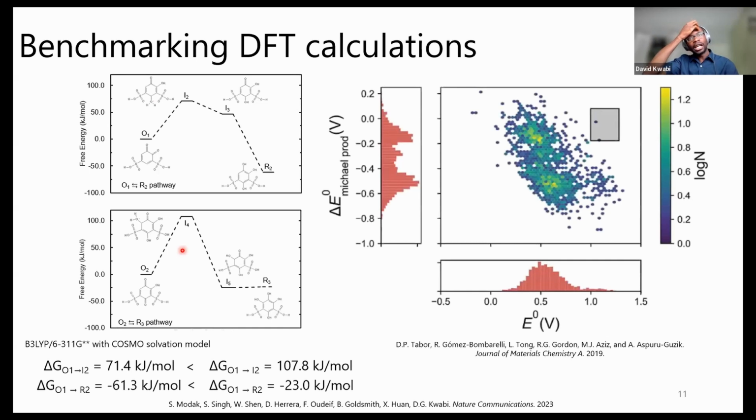Thinking a bit more broadly, I should also mention that there's been some computational work in the literature suggesting that there's some sort of trade-off between a quinone's susceptibility to Michael attack and redox potential. You can see here that as we increase our redox potential, the free energy for Michael attack is more and more negative. So this is a trade-off that has been hypothesized in the literature, but careful measurements of the kinetics that I've shown just now in principle can help substantiate this relationship. And perhaps we can actually find molecules that break this apparent scaling relationship between redox potential and the Michael attack reaction.